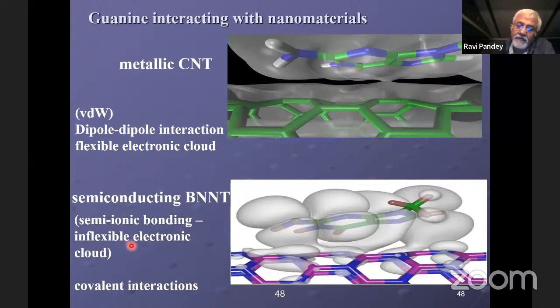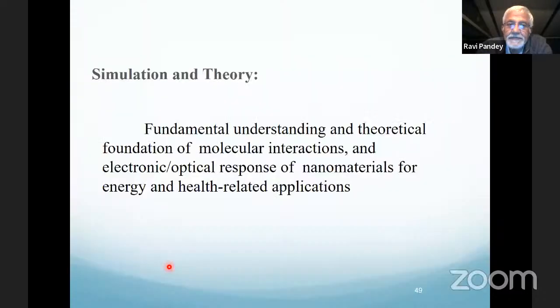And what we also have for boron nitride, because of the semi-ionic bonding nature, is that the electronic cloud is not flexible enough, like we have for CNT. So they have more or less a covalent type, or what we call the polar pi interaction, in the boron nitride case. So you can really go system by system and look in detail at the nature of the bonding. And because of this, then the response to different external fields, in terms of either electronic devices, optical devices, or biotechnology sensing devices.